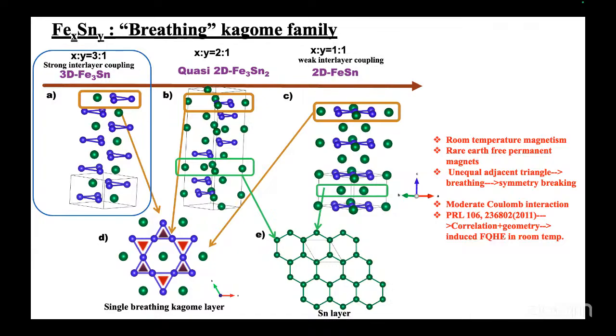So in your future direction, you say you want to study the effect of electronic correlation on the Berry curvature. But I thought you have the DFT calculation already. But with the present code, we cannot calculate the Berry curvature and the anomalous Hall effect. But these results can tell us that there is a shifting of the Weyl nodes, and if we can calculate the Wannier projection and feed it into another code, we can find that. The DFT code only gives the energy spectrum without the wave function, so it does not support this Wannier calculation.